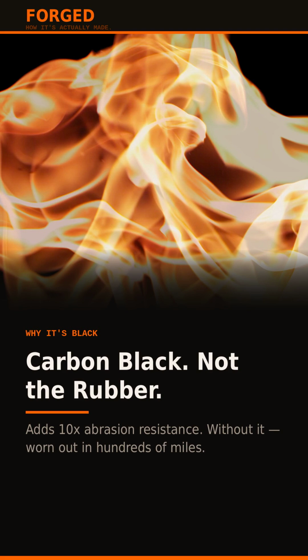Natural rubber is a cream or tan color. Every tire you have ever seen is black, and that color comes entirely from carbon black, a fine powder that is almost pure carbon, produced by burning hydrocarbons in low oxygen conditions. It is added to the rubber compound in significant quantities, and it transforms the material. Carbon black reinforces the rubber matrix at the molecular level, increasing tensile strength and abrasion resistance by roughly a factor of 10. Without it, a tire would wear out in a few hundred miles. It is the single most important additive in the compound.